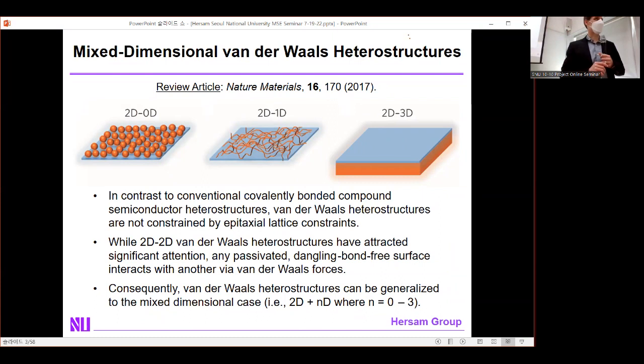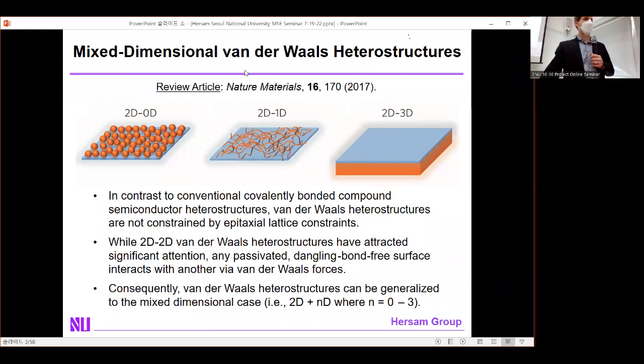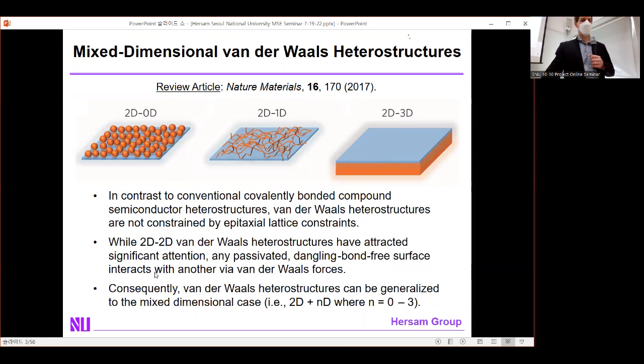This is enabled by the fact that the bonding between these materials is van der Waals bonding, leading to the concept of a van der Waals heterostructure. The great advantage is that you can now form an atomically sharp, well-defined hetero interface without worrying about epitaxial lattice matching, which constrains compound semiconductor heterostructures. This concept is very popular in the 2D materials field.